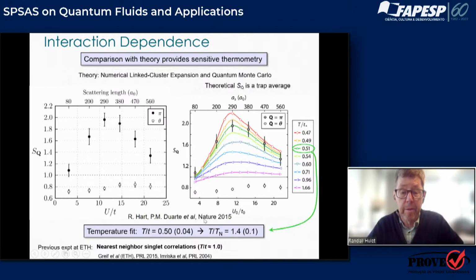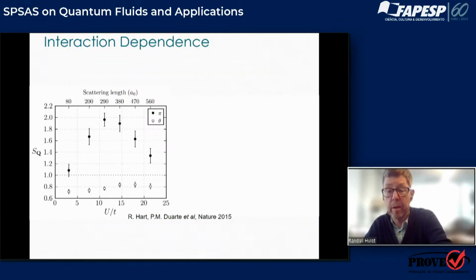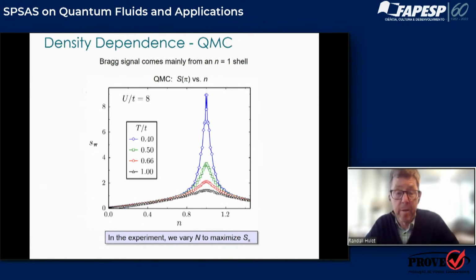So the temperature is about 0.5 in units of the hopping. And it's known from the theory that the transition temperature is around 0.37, I think it is. And we're at about 0.5. So we're above the Néel transition, but not so far above it that we don't already see the development of magnetic correlation. So there are magnetic correlations that are happening. They're just at a region which is a little bit lower down on this plot, very close to the green peak. And we would like to be at the Néel transition, which is very close to this blue one.